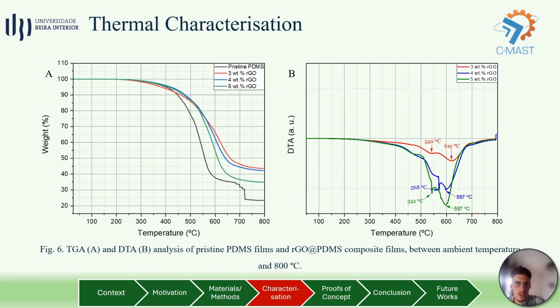Regarding the thermal characterization, the TGA test on the left allowed us to conclude that the rGO content greatly influenced the thermal stability, where although the degradation temperature was similar for all, at around 400 degrees, the temperature at which the samples lost half their mass and the final residue was much higher for the composites, and especially for the 3% rGO sample. On the other hand, the DTA curves on the right allowed us to observe that the degradation was accompanied by endothermic peaks, peaks that could allow us to predict the mass drops in the TGA, while also observing the thermoset-like behavior of this material.